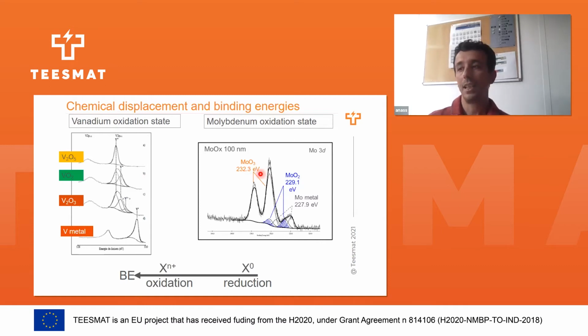What we can see here is that the more the molybdenum is oxidized, the more the shift goes to higher binding energy. By the same analogy, here we have different vanadium oxide materials: vanadium pentoxide, VO2, V2O3, and metallic vanadium. In V2O5, the vanadium is in the 5+ oxidation state, so it is located at higher binding energy. For VO2, we are in the 4+ oxidation state, so we have a shift to lower binding energy, and the more we reduce, the more we go to lower binding energy. So for battery materials, it's a redox process at the end, so what we look at is the reduction of metal oxide materials. XPS from this example can be one of the powerful techniques to probe the oxidation state of materials during lithium insertion or de-insertion.